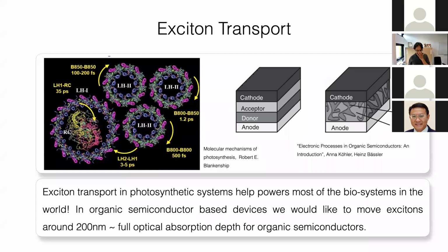And as you know, empirically, we've had a lot of success with this. Organic photovoltaics have now reached about 19% single junction efficiency, which is really incredible actually, if you think about it. But the formation of this bulk heterojunction is very complicated. Its long-term phase stability is also a complex problem. These kinds of materials, of course, from a thermodynamic point of view, want to phase segregate over time. So maintaining this structure is challenging.